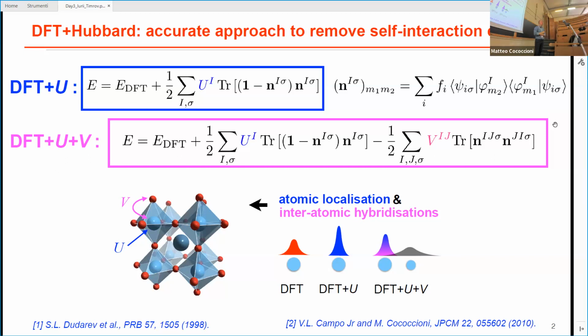It's for sure more flexible, with more degrees of freedom to play with. I don't know if it's important, maybe in some systems. I think it's important when you have light elements like the p-block. In that case, I think you need that, like gallium arsenide, silicon, you really need these kinds of cross terms. Yeah, we needed that mostly because of sp3 hybridization.